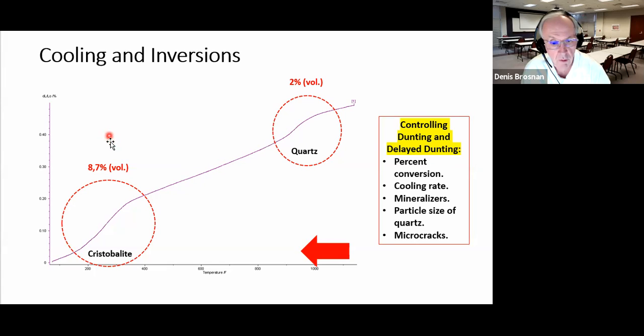Of course, I also talked about delayed dunting in porcelain products, which can happen minutes or hours or days or years later from when the product was made. In other words, this dunting process can impart stress within the ceramic, and eventually cracks can link up and cause failures. And so sometimes toilets will fail, but not very often. I mean, this is a very small amount of time by delayed dunting, and it can make the products weaker.